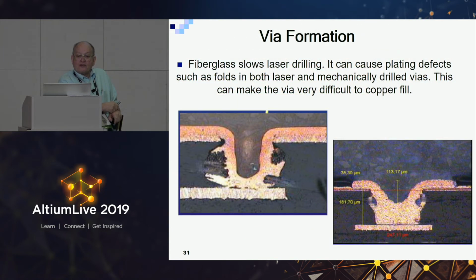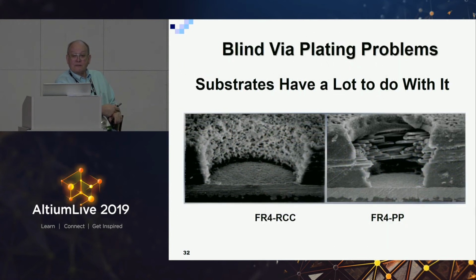Some via formation. This is an example of bad via formation. You notice how they ripped up the copper layers with the laser, and they've broken the layers of the glass apart. You don't want to see this in your boards, because this stuff is headed towards field failure, under warranty kind of stuff. Blind via plating problems. This is FR4 resin-coated copper versus FR4 that has glass and prepreg.